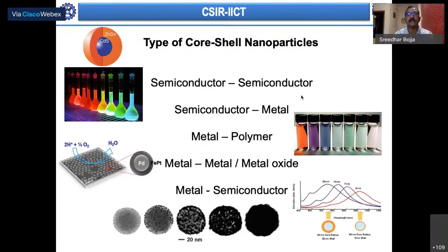These core shell nanoparticles, depending on the material, have different forms. If you have a semiconductor core shell, or semiconductor, metal, polymer, metal oxide, or metal-semiconductor kind of material, depending on the type of material used for your applications, you have various core shell nanoparticles. As you can see in this example, initially you can see the core, but once you start to coat the shell layer after layer, you can see only the shell, not the core, after a few coatings with this material.